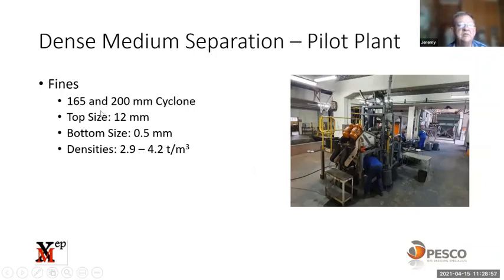For the fines, there's a 165 cyclone and a 200 millimeter cyclone. They can handle a top size of 12 mil, a bottom size of 0.5, and also the same range of densities, again using different medium grades than you would with the drum.